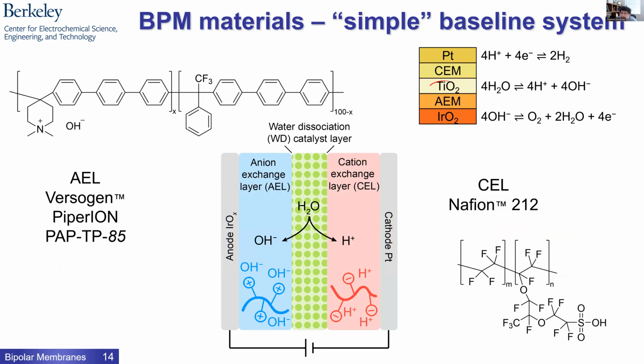We did a lot of work on TiO2 catalysts. These can be thought of as a layer of nanoparticles that are sandwiched by these two polymer films. It's all filled with water, so you should think about these particles, and they're going to be 5 to tens of nanometers in diameter on average. They're often crystalline metal oxides, flooded with water, and pushed between these two membrane layers.